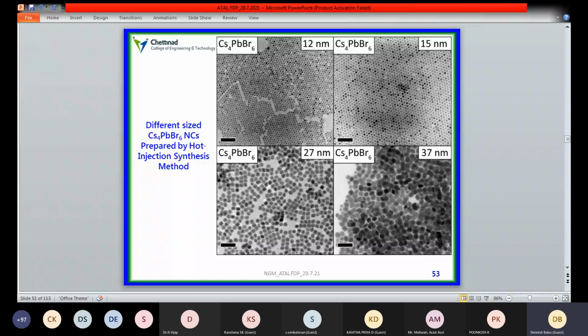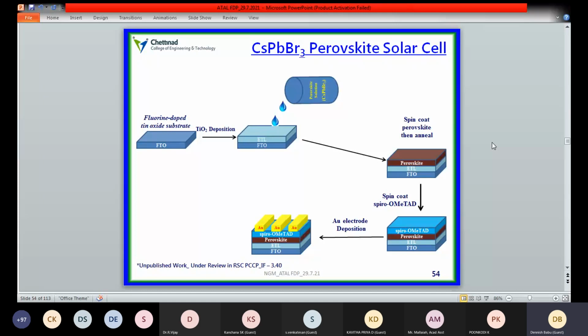Yes, sir. So these are the different cesium lead bromide based systems that we have prepared with the help of hot injection methodologies. We have achieved some fine size-controlled structures in the range of 12 nanometer, 15 nanometer, 27 nanometer, and 37 nanometer. Some kind of nano heterostructures, like very small nanorods and nano pentagon shaped structures, are also observed from the STEM images. After that, we have fabricated these perovskite solar cells by adopting simple spin coating methodologies. So we have taken a fluorinated tin oxide substrate and we have deposited mesoporous titanium oxide material with the help of a simple spin coating method.